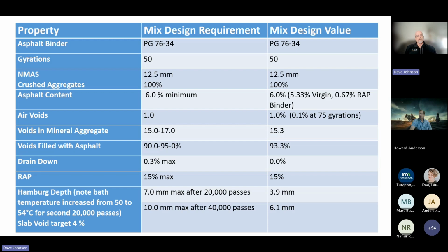The allowable range for VMA, as we can see, is 15 to 17. They were towards the lower end of that at 15.3. With those other volumetric changes, that requires a change in the VFA. The range, as we see there, is 90 to 95. This one came towards the middle of that at 93.3. They did a drain down test with that higher asphalt content. They wanted to make sure that there weren't going to be issues.